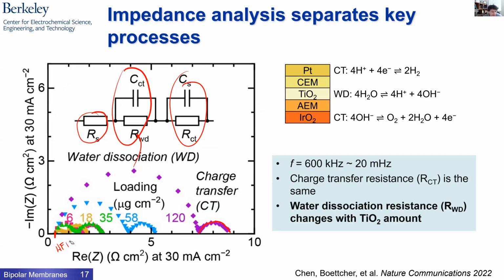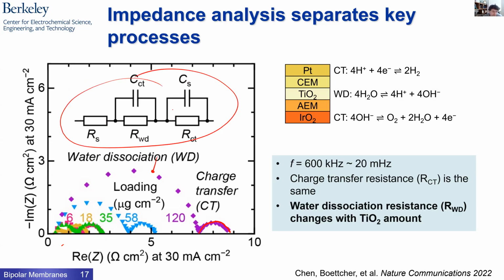So you can look at these curves very quickly. You can fit these data. There's always some concern when you're mapping data to a model like this. But one nice thing that we can do is change the catalyst loading, and we can see that this arc doesn't change as I change the amount of catalyst in this layer. And so that's definitely the RC element that's associated with the two electrodes. It's a lumped element. You can't separate it in this case.